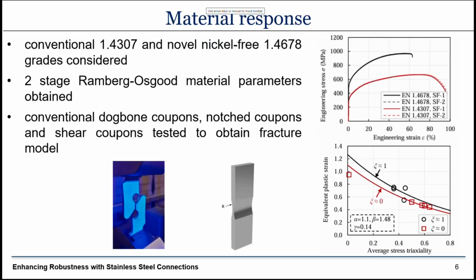We initially considered 2 stainless steel grades, conventional 1.4307, which is 304L in the American designation of stainless steels, and a more novel nickel-free austenitic stainless steel grade, which is EN 1.4678, which has the commercial designation of H500. Here we can see the obtained stress strain curves for the 1.4678, the novel nickel-free stainless steel, and the more conventional austenitic stainless steel grade.